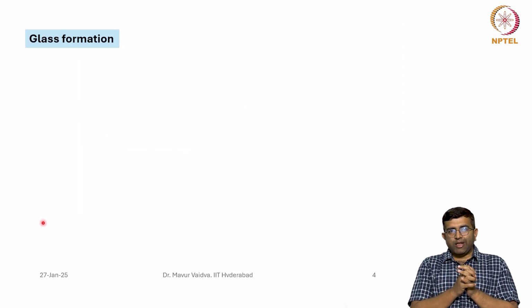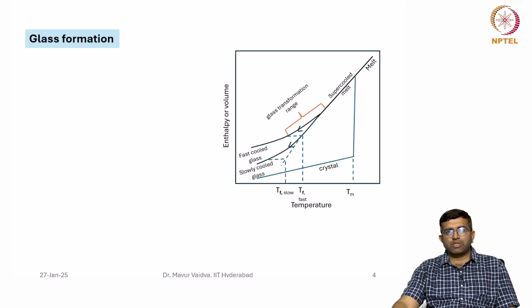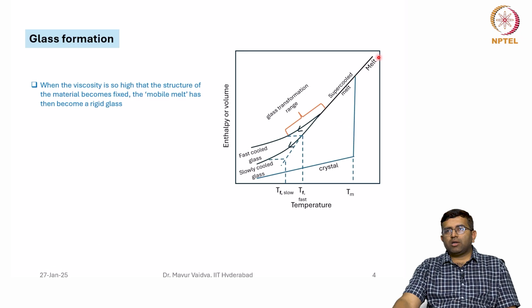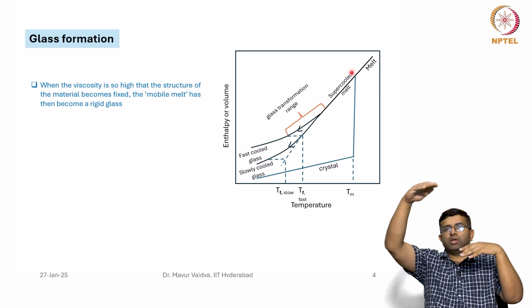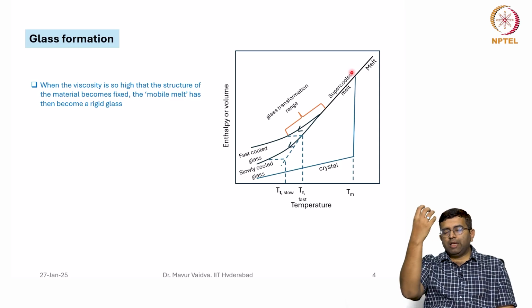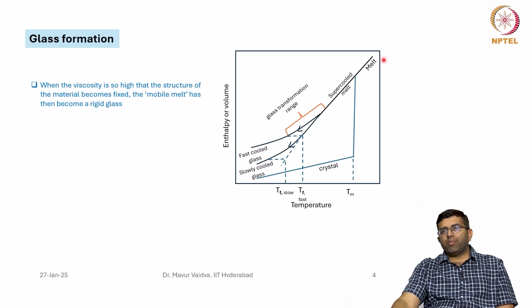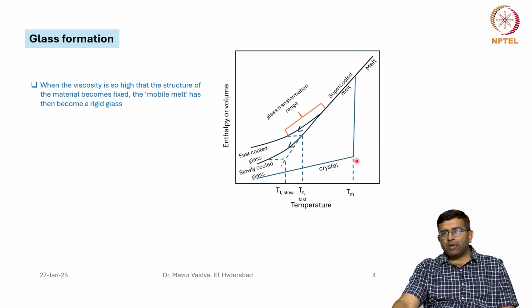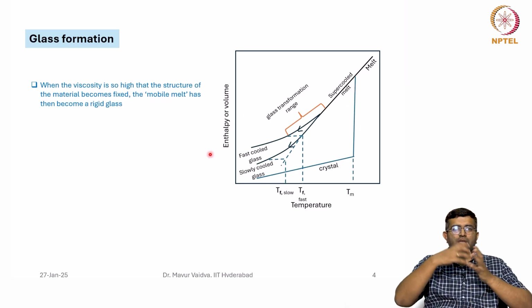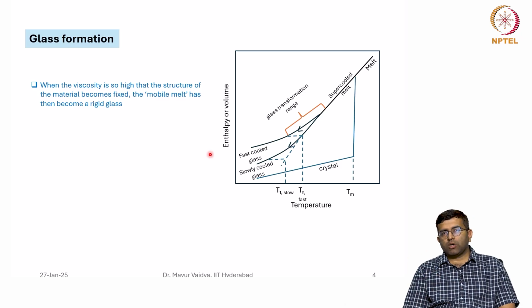Now, let us talk a little bit about how the glasses form, thermodynamically how the glass formation happens. So, for example, if you take a melt which is way above the Tm, and as the melt slowly cools down and comes to the melting point, below the melting point the melt would try to crystallize. Then the enthalpy or the volume will decrease drastically. There will be a sudden jump in the volume and enthalpy, because you know that enthalpy is released when liquid transforms to solid. Similarly, there is a considerable volume reduction when this transformation happens.